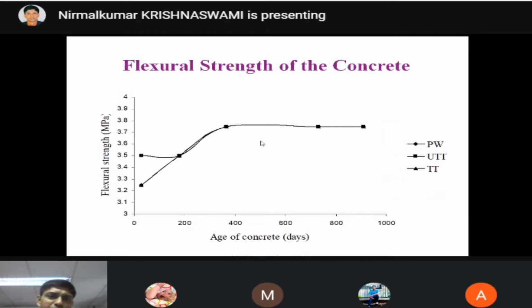Then coming to the flexural strength, I cast 100 centimeter bars with a 10 centimeter by 10 centimeter section. Without using any RCC, I just used the PCC, and this is the flexural strength. Here I had used the admixture, but there is no adverse effect, so I have not given you the comparison. Just you can see these three things.